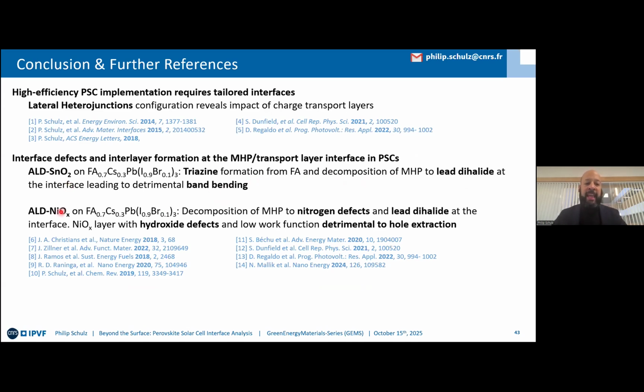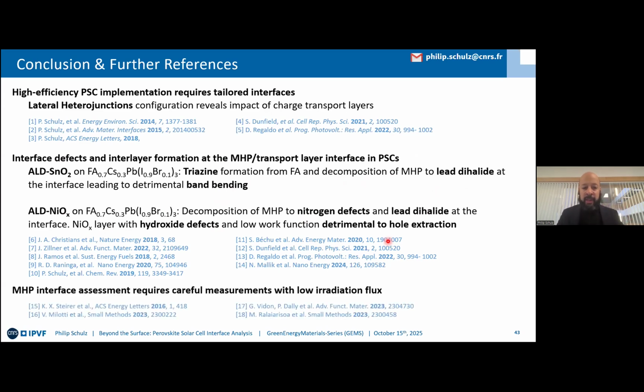Whereas in the case of ALD nickel oxide, yes, we also see these nitrogen defects and lead dihalide formation, but this time we don't see strong recombination, but it's the defective nickel hydroxide layer that is detrimental for hole extraction, which we can, however, circumvent by buffering the system. And overall, this interface assessment, as I presented it, requires careful measurements, low irradiation flux.